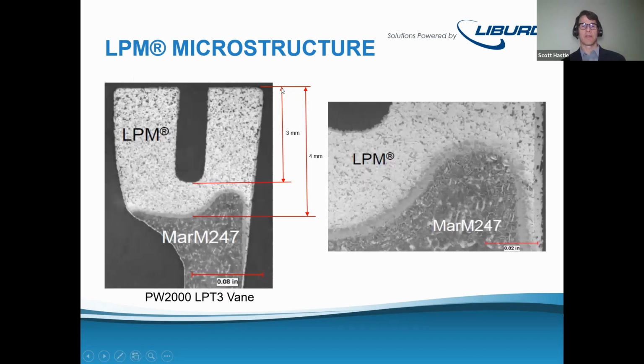Just to give you an idea of some of the depth that we work to, this is 3 millimeters thick and 4 millimeters thick to the bottom. We apply material, and I'll show you some pictures on this in the next slide, to the seal slots and do a build up, and then re-EDM that seal slot back into shape.